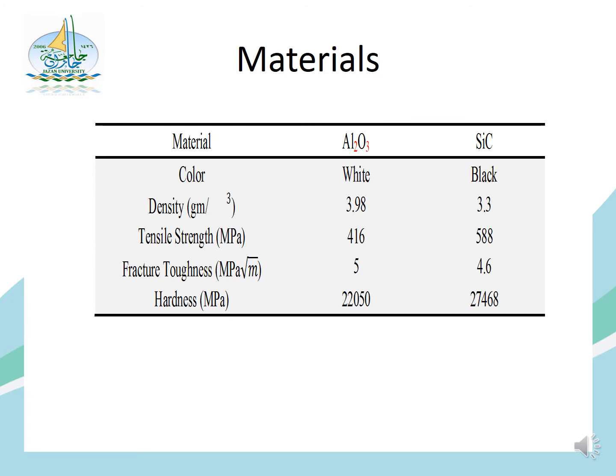So, for the materials, a composite material containing a commercial resin that we got and the hardener with additive nanoparticles. Also, to achieve the complete hardening of the epoxy, a 12% hardener was used, as described by the manufacturer. Also, before adding the hardener, the nanoparticle types with various percentages were thoroughly mixed in the solution. So in this study, aluminum oxide and silicon carbide nanoparticles were selected as nanoparticle additives. These were purchased from an international group in China.